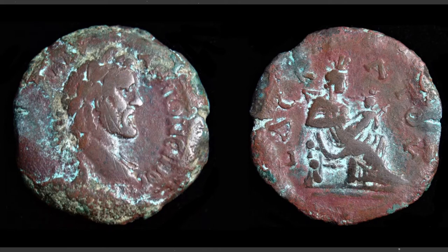These coins have bronze disease. Trust me, you can't get this disease unless you are made of bronze. Bronze disease is the corrosion of copper and bronze objects caused by the production of copper chlorides, which break down the normally protective surface patinas. You will notice light blue-green blisters form on the surface. When touched, they crumble and fall away, leaving a pitted surface. The corrosion is cyclic, setting up reactive and destructive corrosion cells on the surface of the metal.